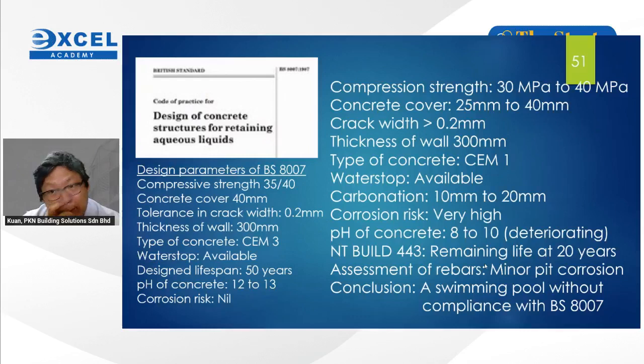Carbonation started not long ago, so it is 10 mm to 20 mm. But the corrosion risk is very high based on the half cell corrosion mapping. pH of concrete between 8 to 10, we can see it is deteriorating. The NT Build 443 actually told us the remaining lifespan of the contaminated swimming pool is left with 20 years only. Reinforcement steel bar, based on physical examination, there is minor pitting corrosion, and the conclusion is the swimming pool was not constructed based on the standard.